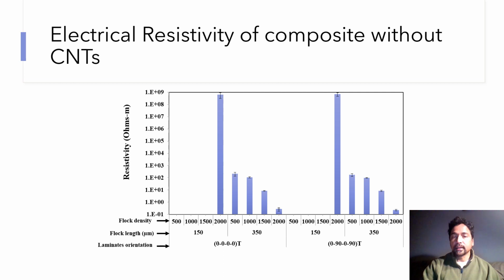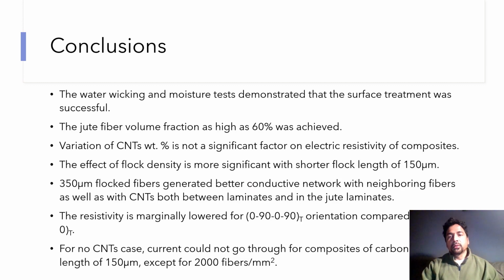So this is a good observation that without carbon nanotubes, you should be able to generate a conductive network within the composite of carbon fibers of length 350 microns, even with a flock density of 500 fibers per millimeter square, which is really exceptional. Hence, I would like to conclude this presentation with a few conclusions here. So water wicking tests really demonstrated that surface treatment was very successful. We were able to make it hydrophobic, and we achieved a jute fiber volume fraction of as much as 60% in these composites, which is not common in previous studies. And variation of CNT amount of 0.1% and 0.025% has no significant effect on the electrical resistivity of the composites. And the effect of flock density is more significant for the shorter carbon fiber length of 150 microns.